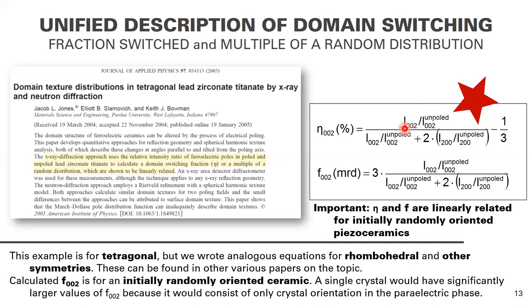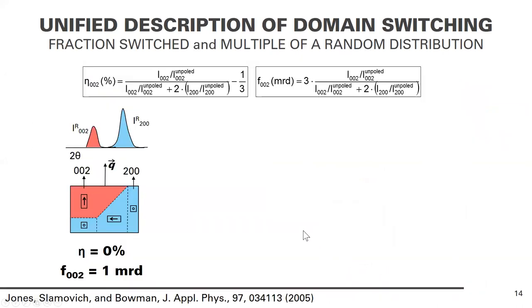Okay. And then we take the intensity of the 002 and the 200 for tetragonal, for example, and we calculate the degree of domain switching that's occurred in a particular direction of the sample. Equivalently, you can take that same base equation and calculate the multiple of a random distribution. And you can readily see from these two equations that they're correlated. Okay. Now, this example is for the tetragonal material, but we wrote analogous equations for a lot of other symmetries in subsequent papers.